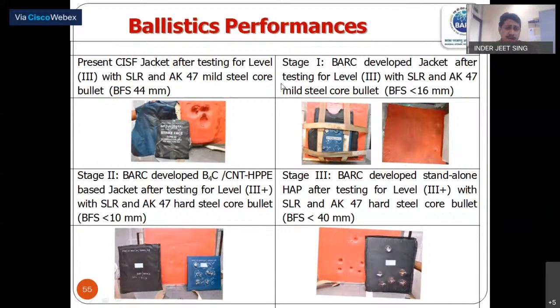So here I am showing some pictures. See the leftmost side, this is what is typically used nowadays, what CISF was using. So this much dent was there with SLR and AK-47, and when Bhabha Kavach was used against them, you can see a very small amount of what is called backface signature. Now this is level 3. I have not explained the levels, because as the level increases, the bullet caliber and threat level increase. I am just showing how Bhabha Kavach improves over the present bulletproof jacket. And when we used boron carbide CNT, it was almost nil, very negligible.